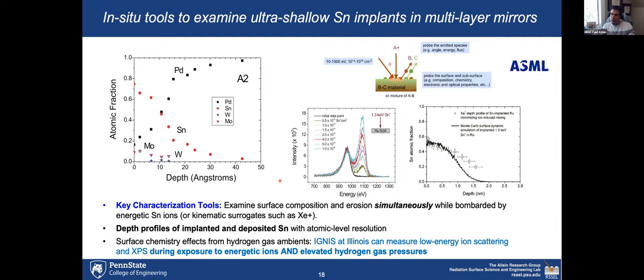There were a lot of conjectures thinking that basically the tin atoms just deposited on the films and it was a matter of just cleaning the film. But we later found out that cleaning the film was not trivial, it was very difficult. So we found from our studies that there was a combination of energy and fluence that allowed the tin to self-clean. And we found this by doing some in-situ probing of the first layer of atoms.